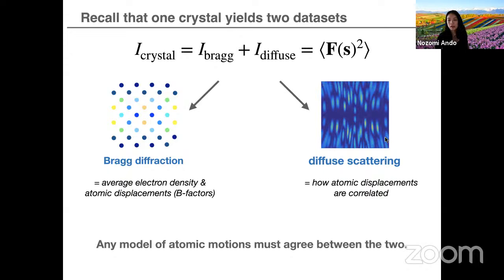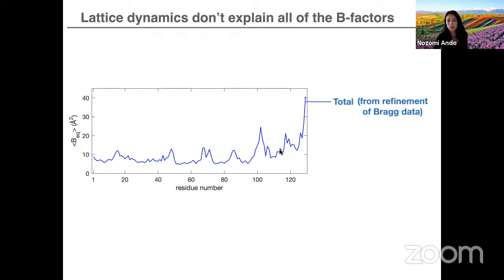And Steve actually did something clever, which was he took the lattice dynamics model that was fit to the diffuse scattering, and then asked the question, does it agree with the B factors from Bragg diffraction? So that's what he did here. What I'm showing in blue is the B factors from the refinement of that lysozyme structure, just from crystallographic refinement. And this is B factors as a function of residue number in the protein chain. So it's kind of like a spiky curve.